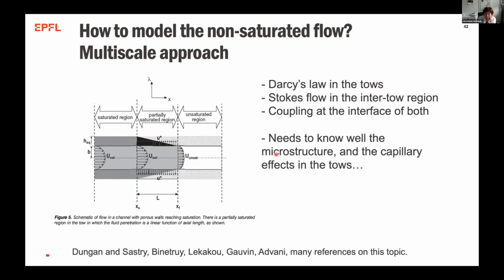But this needs to, of course, know well the microstructure, which now with CT scans you can, but the capillary effects in the tow, because then how does it impregnate here? And what again, the delta P gamma that you have everywhere is a bit of a catch-22. So it can be done, but it's again a bit tricky.